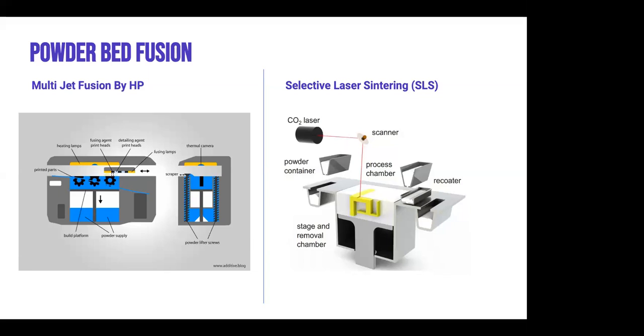An aspect of MJF that is significantly faster than the SLS is in the bin cooling and the post-processing. HP offers a dedicated post-processing station that speeds up the cooling rate of the printed bin and helps in powder removal. In the multi-jet fusion process, the recovered powder can be 80 to 85% recycled and reused, while in the SLS process, only 50% of the powder can be reused. Faster cooling times and greater recyclability mean that MJF operators are less hesitant to start the job when the bin is partially full. While in an SLS, the machine operators often wait for the bin to fill before they start the printing activity. This key difference in the workflow results in shorter lead times of production.